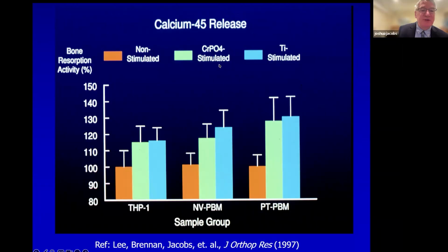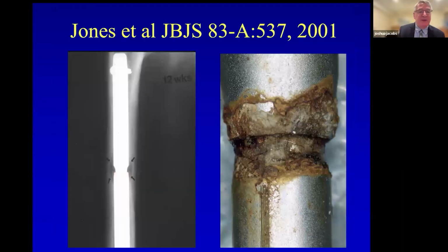And these corrosion particles turn out to be very stimulatory and can cause periprosthetic bone loss similar to other fine debris, including polyethylene. And in this system there's no polyethylene and no bone cement. So the only particles generated in this system, which is an intramedullary rod to treat a femur fracture, a modular stainless steel nail, you can see this periprosthetic osteolysis associated not with polyethylene or bone cement, but actually with corrosion debris from this stainless steel rod and this modular connection.